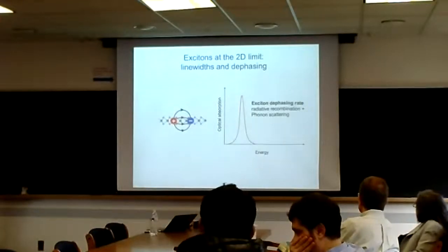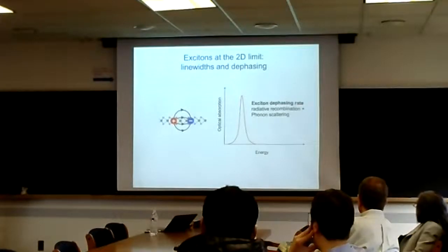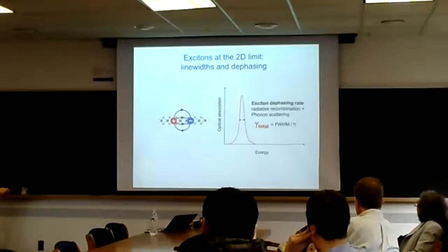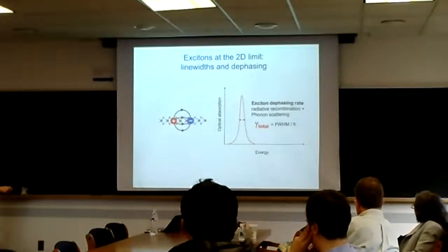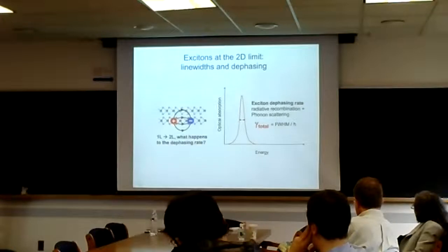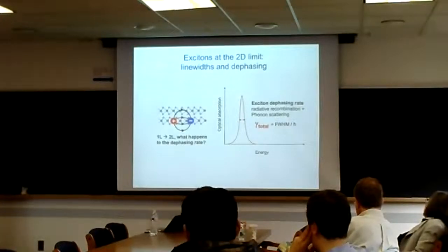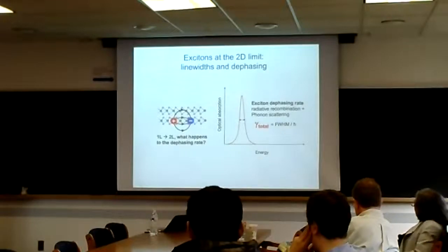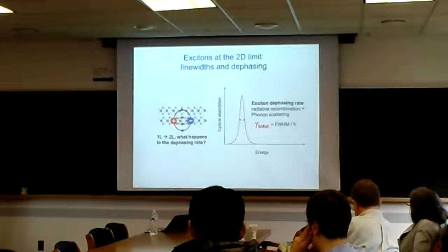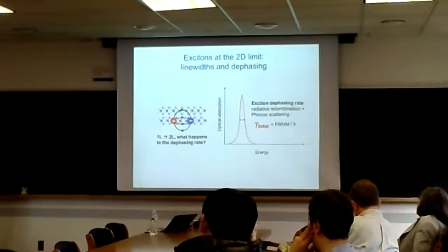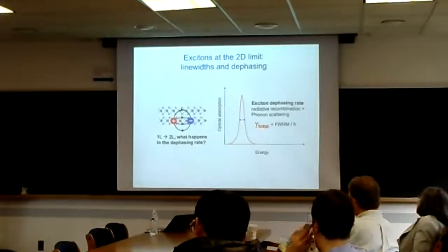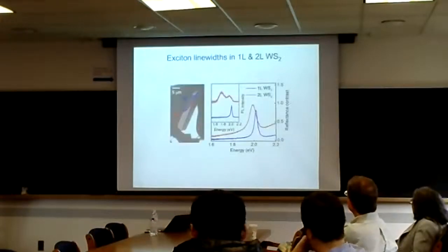So this is again a schematic. You have an exciton in these materials, so you have a peak, and the radiative rate plus phonon scattering tells you something. The line width informs you about these processes, the radiative recombination and phonon scattering. Now, when you add an extra layer, what happens? Of course the electronic structure changes. But what I want to show you today is that going from indirect to direct gap itself wasn't the crucial aspect for changing the phonon interaction, but in fact, having this unique screening is what contributes to a change in the dephasing rate here.